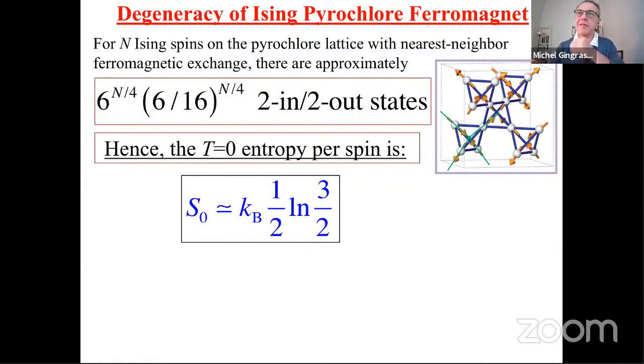This is illustrated here in the top right figure. If you look at, for example, the top left tetrahedron here, I hope you can see my mouse, the 2 bottom spins are pointing in, and the two top spins are pointing out. So this tetrahedron has a local magnetization along the plus Z cubic direction. And so you have 6 such orientations of the magnetization. Either the magnetization on that tetrahedron is along the positive Z or the negative Z direction, and similarly for the X and Y directions. So if the tetrahedra were not connected, then in a system of N spins you have N/4 tetrahedra, and you would have 6^(N/4) ground states. But these tetrahedra are not independent.